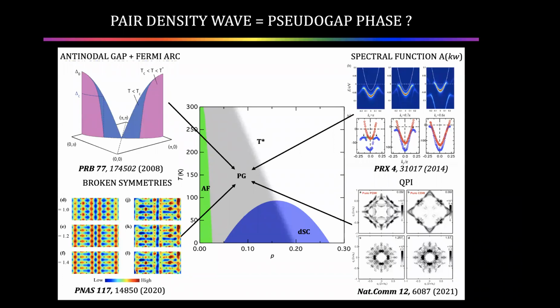We know that, for example, the Heisenberg magnet in two dimensions has a huge region of long correlation length, and that you can do a pretty good job of describing it using mean field theory on short distances. So presumably, the fact that these mean field theories seem to do a halfway decent job on describing the data, but there's no supercurrent, means that you've got such a theory that loves to create long correlation lengths, but without locking in as true long range order. It's quite unlike an Ising order parameter, for example. Once it starts to develop, it just goes zoom into long range order.